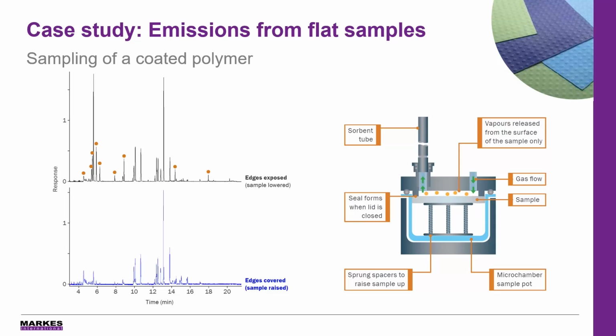And then in the bottom trace, the blue one, what we've done is cut out a sample, raised it up inside that microchamber, closed that lid down, and given us that defined surface area that we're looking at. And in doing so, you can see that we have removed the emission profile of all of those compounds with the orange dots that we saw in the bulk emission.